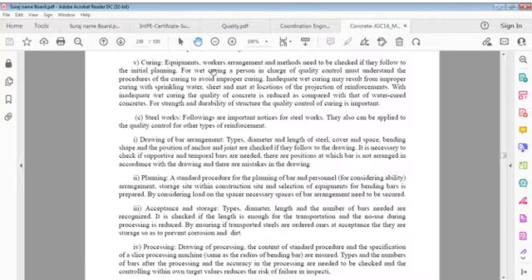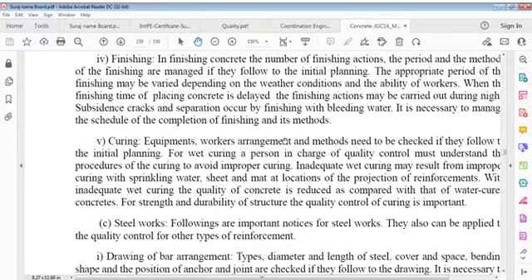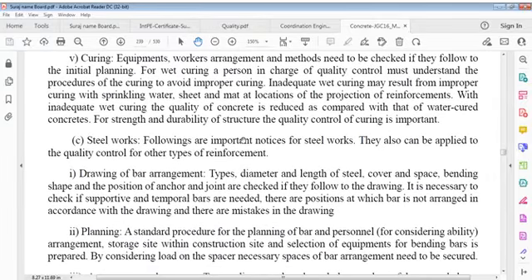Curing, we have to continue. It's a very important item. We have to see curing equipment, workers, arrangement and methods, and check if they follow initial planning. For wet curing, a person in charge of quality control must understand procedures of curing to avoid improper curing. Inadequate wet curing may result from improper curing with sprinkling water, sheet and mat at locations of projection of reinforcements. With inadequate wet curing, quality of concrete is reduced as compared to that of water-cured concrete. For strength and durability of structure, quality control of curing is important.